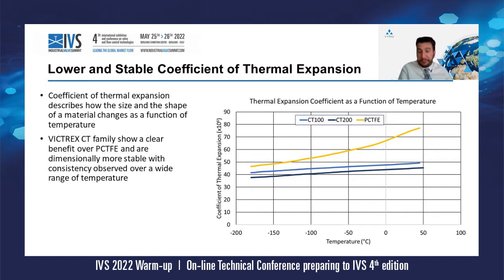So, we can stop the comparison around 100 degrees or maybe 120 degrees, where PCTFE is not even usable anymore. While PEEK CT100 and CT200 will continue to work properly up to 150 degrees, 180 degrees, 200 degrees, of course something depending on pressure, with the same behavior you would expect from a common PEEK. So there is no change in the expectations you might have when we are talking about high temperature. The changes have been made especially to allow the performances at low temperature. So we refer to this when we state that CT polymers extend the temperature range of your cryogenic valves and reduce as much as possible any shrinkage or dimensional change.